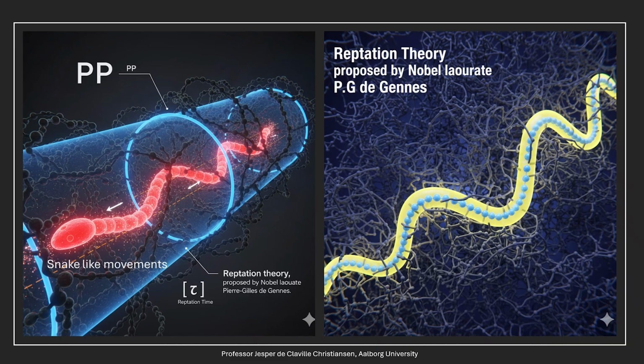One of the main effects when you get these shorter chains is that the movement gets faster. So de Gennes got the Nobel Prize many years ago, where he proposed that polymer molecules move inside a network like a snake in a tube. So he introduced something called the reptation time. And the reptation time is the time it takes for this blue chain that you see on the right-hand side to move out of the yellow tube. And when we degrade and recycle polypropylene, this movement and this time becomes faster.